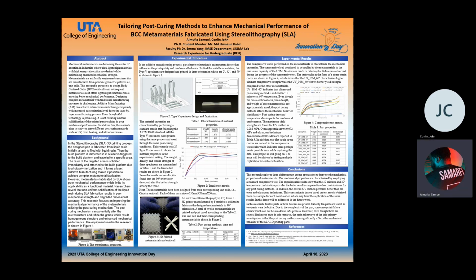When it comes to the results of our experiment, the compression test is performed on the metamaterials to characterize the mechanical properties. The compressive load continued to be applied to the metamaterial to the maximum capacity of the UTM. No obvious crack or catastrophic failure was observed during this process. The test results in the form of a stress-strain curve are shown in Figure 4, which shows that ultraviolet at 10 minutes at 60 degrees Celsius characterizes higher ultimate compressive stress, while ultraviolet waves at 30 minutes at 40 degrees Celsius show higher yield strength compared to other metamaterials.